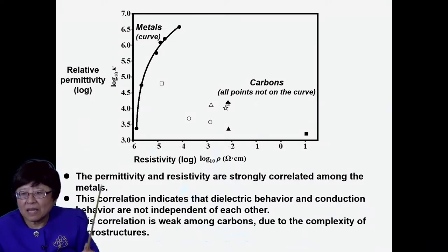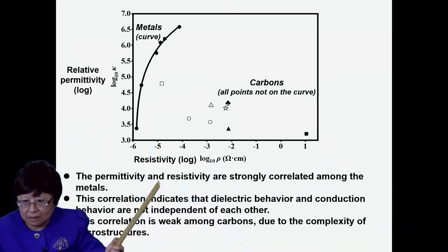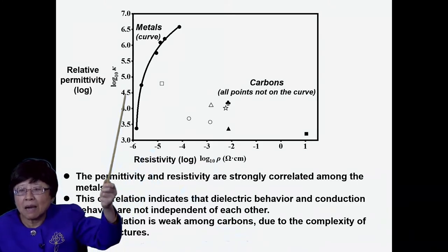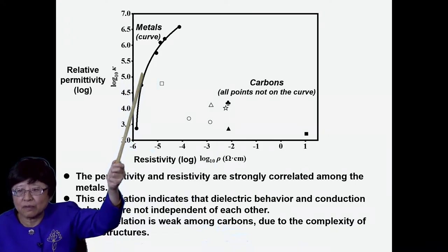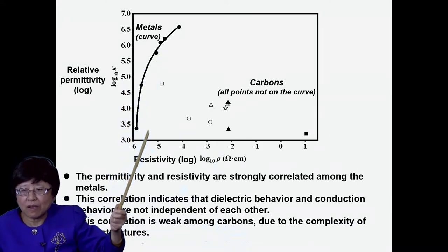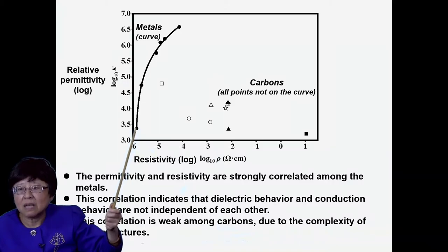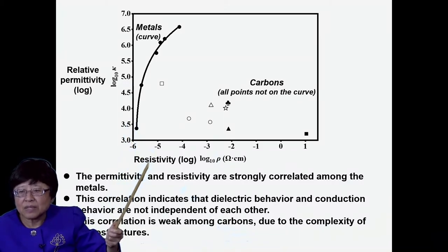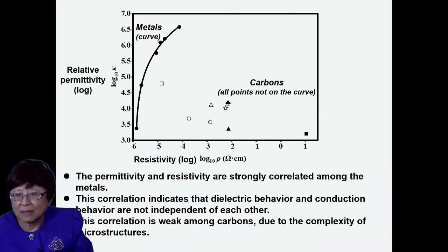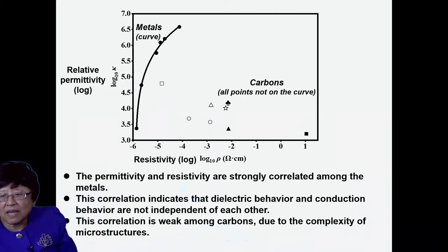The permittivity and the resistivity are correlated pretty well among the various metals. And this curve is for various metals, including steel. The higher the resistivity, the higher is the relative permittivity. And this correlation indicates that the dielectric behavior and conduction behavior are not independent of each other.